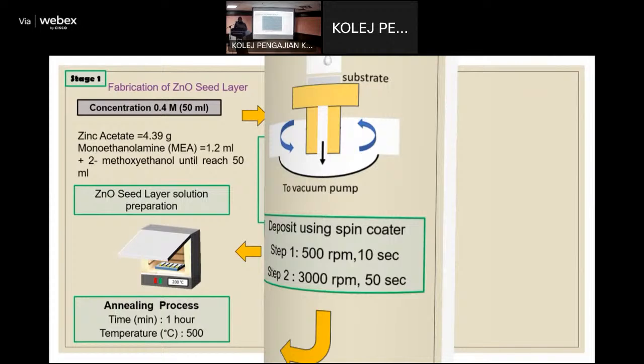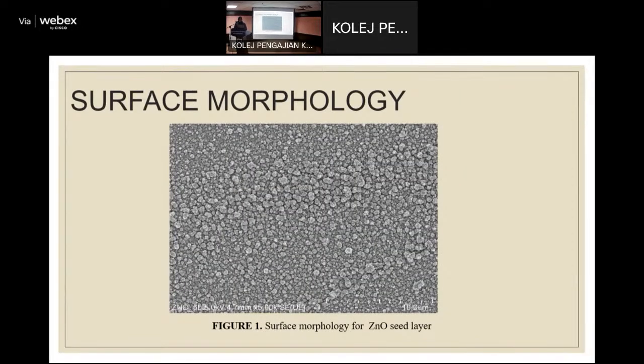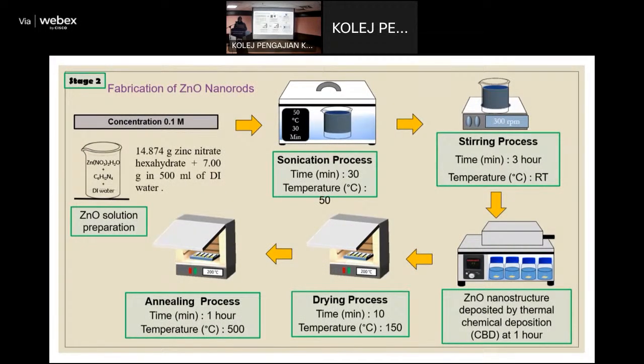Okay, so this is the surface morphology of the ZnO layer that we observe from the SEM. From that we can see that the surface morphology for the ZnO is quite uniform on top of the ITO. Then the second is the fabrication of the ZnO nanorods.